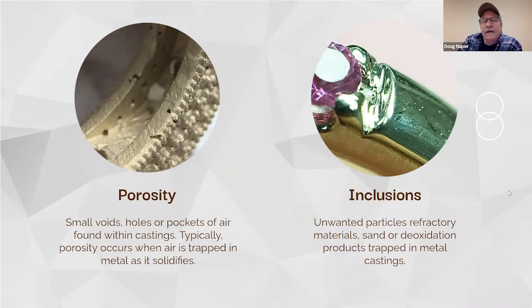Say if you create some coins or something like that has a lot of text in it, you cast it up and you'll look at where the text is, and some of the text areas are broken out and they fill in. And you think, oh, darn, I got to go in and fill it. But what you don't realize is when those little pieces break off, that's investment breaking off. And when that metal comes in there, it's taking those things and it's floating them around and they come to rest at odd places. So you'll see these, again, rectangle and square shaped defects or inclusions in your casting. And that's just the investment that's broken off and gotten into there.